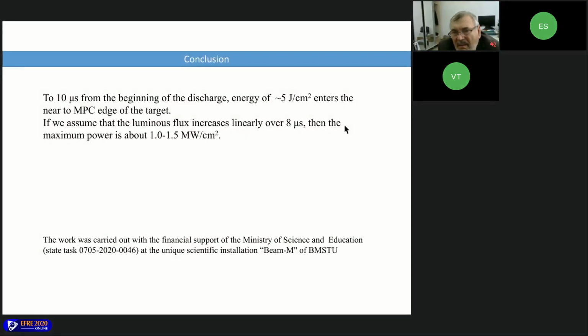And the main conclusion of our research is the determination of energy falling on the targets. If we take in mind our discharge parameters and energetic parameters, at 10 microseconds from the beginning of the discharge we have 5 joule per square centimeter, and that's near the threshold of the targets. And we think that the luminous flux increases linearly up to 8 microseconds, when the maximum power is about 1 or 1.5 megawatts per square centimeter.